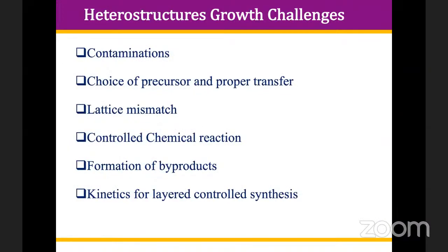Then we tried to make heterostructures of the 2D material. Is it possible or not? Because for 2D material, the growth itself is a challenge, but we attempted: can we make heterostructures of 2D material? And always, to make heterostructures of 2D material, there's a problem of contamination, interface problems, choice of precursors and proper transfer from one location to the other, lattice mismatch between the 2 layers, and controlled chemical reactions. There should not be any interdiffusion between the 2 layers, and because of interdiffusion, there's a possibility of formation of byproducts. And then kinetics for layer-controlled synthesis is very crucial.